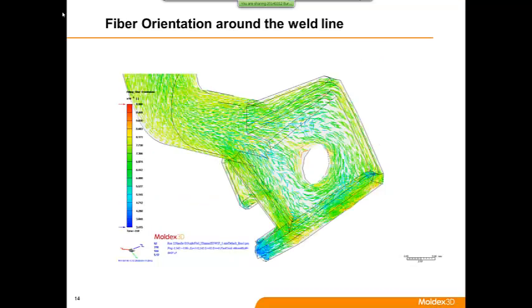For example, we can also show from this chart the green lines, the vectors suggest the fiber orientation. And the melt front is going from the right-hand side, passing through that circle and joins on the left-hand side. You can see the fibers align almost in parallel. So at that weld line location, no fiber is crossing that weld line. This creates a very weak area over here. And what makes it worse is this always happens surrounding the hole.